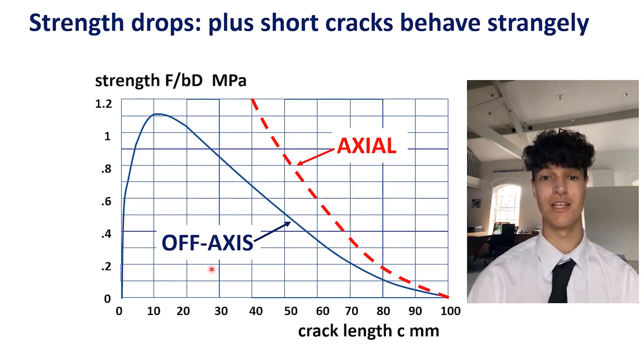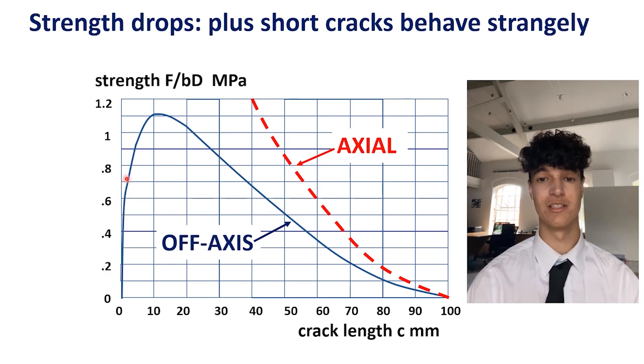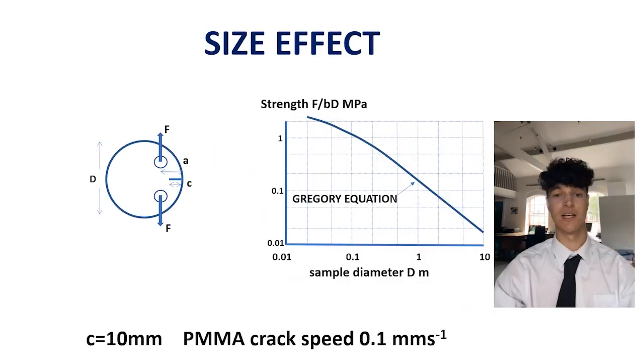But the most interesting change is that small cracks now behave differently. The force is 0 for a 0 crack length, whereas Griffith's force goes to infinity. This gives a size effect in which the disc gets weaker as it gets bigger, using equal crack lengths. But such size effects exist in bending cracks, compressive cracks, and adhesive joint cracks.